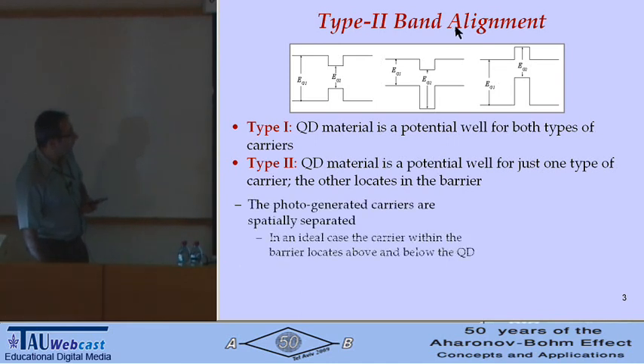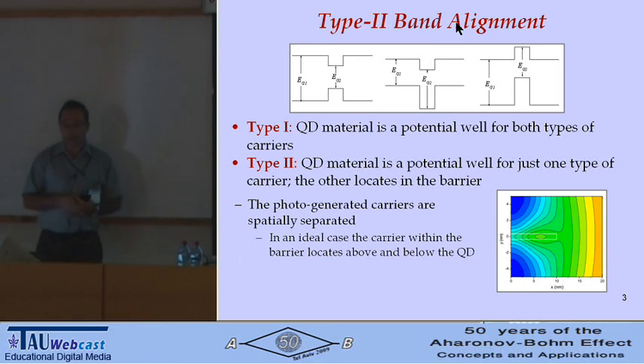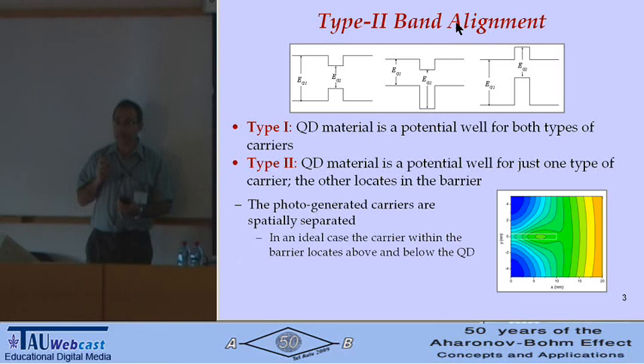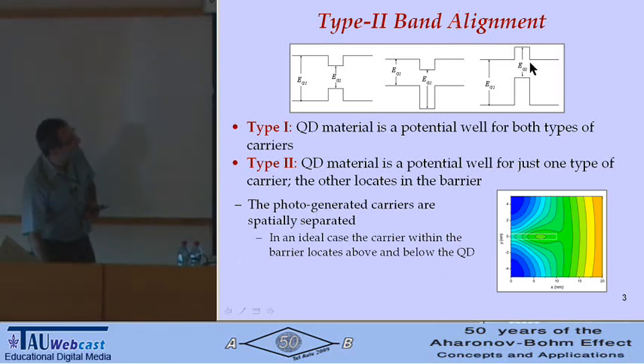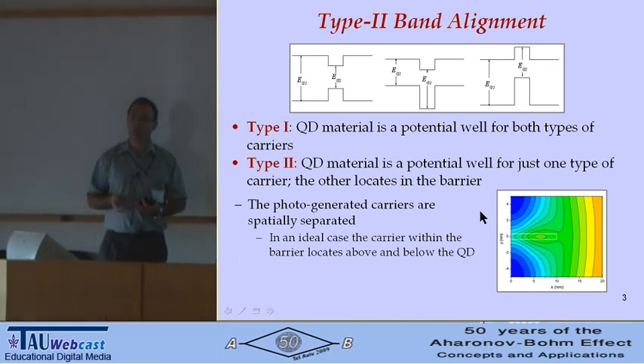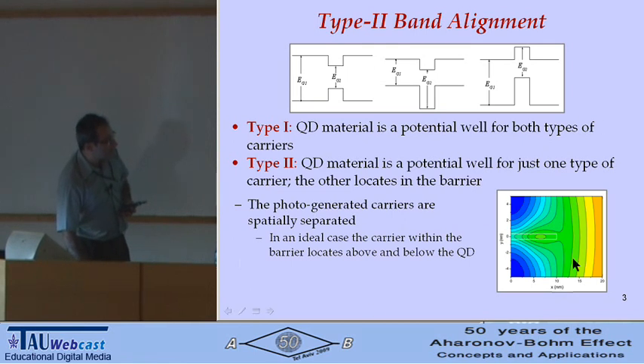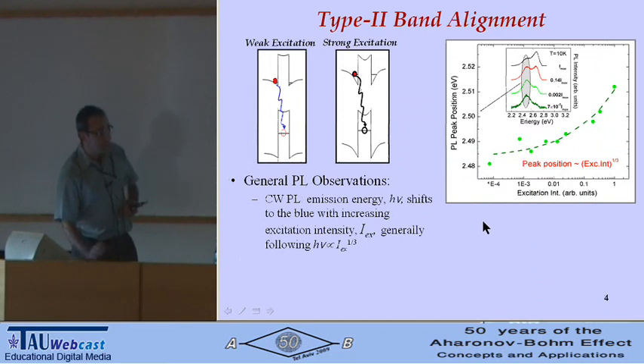Interestingly, if you look at a perfectly ideal type 2 quantum dot, in this case, since our system is of this type of band alignment, as I'll show you later, you can do the calculations, and you can show that if that's the z direction, the growth direction of an ideal single quantum dot, the electron would sit on the top and the bottom of the quantum dot. So if you apply a magnetic field along the growth direction, you will not be able to see the Aharonov-Bohm effect, because you need cylindrical geometry. So in this case, stacked quantum dots would be very useful.